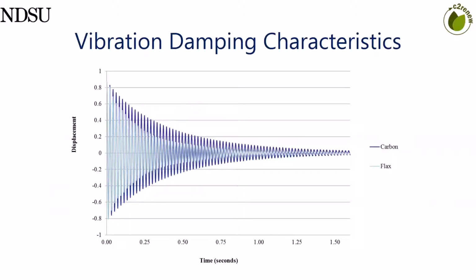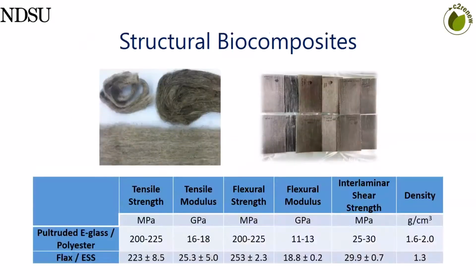Another great aspect is the vibration dampening I talked about earlier. This shows a cantilever beam that was excited, one made with flax fiber and one with carbon fiber. As you can see in the lighter color, the flax dampens those vibrations much more quickly and dramatically than the carbon fiber structure. That's the benefit that hybridizing these two materials can provide in your final composite application.